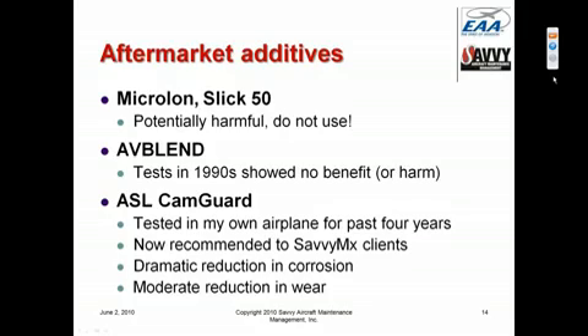There's an additive that I started testing in my own airplane about 4 years ago called ASL CamGuard that I am very impressed with. After I used it for about 3 years, I started recommending it to our managed maintenance clients, and we now have several hundred airplanes that are running with CamGuard as an additive. The major claim to fame of CamGuard is that it is a very, very effective corrosion inhibitor.